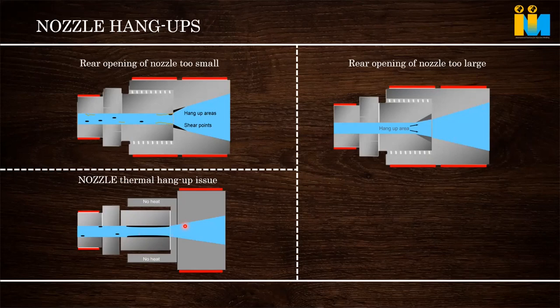Sometimes when we are changing raw material from a highly viscous raw material to a lower one, for example if we are running a polycarbonate and after that we are running PP, some amount of polycarbonate will stay and make a scaling inside the nozzle. The other material cannot push it out. So after some time it burns, stays there and burns for a long time, and it can come out. These problems are sometimes very difficult to attend, but how to optimize it?